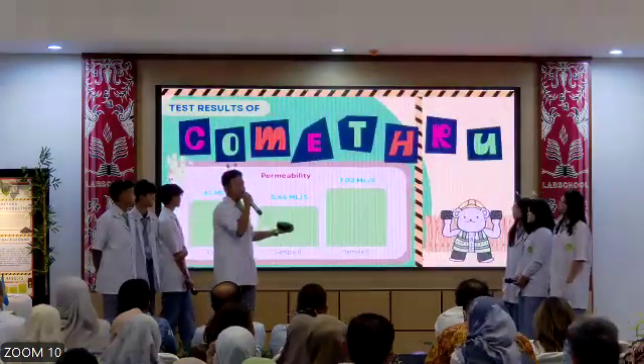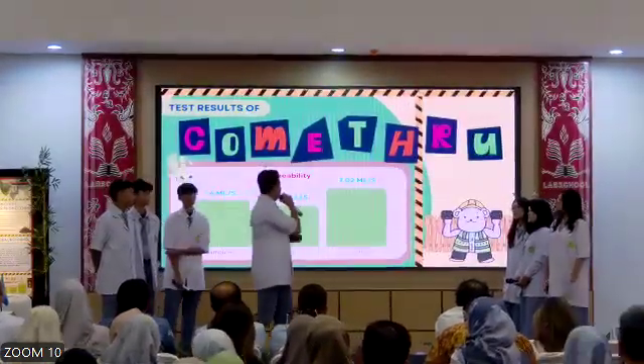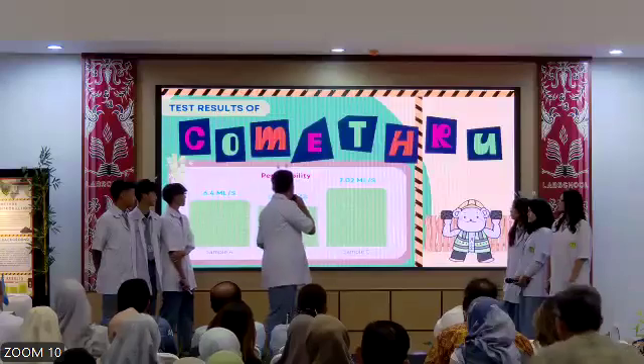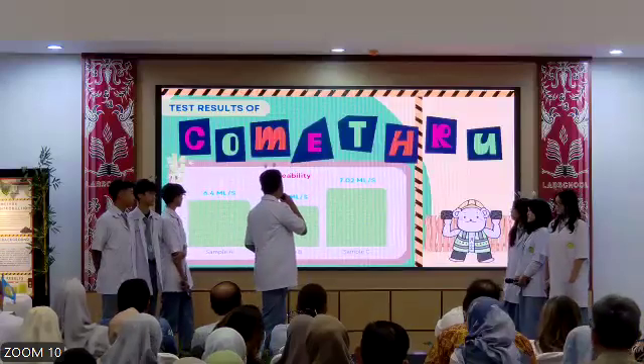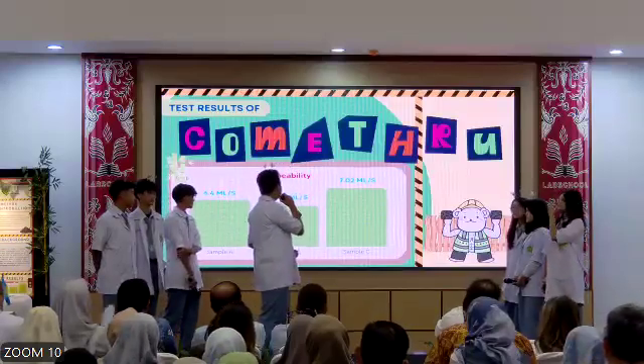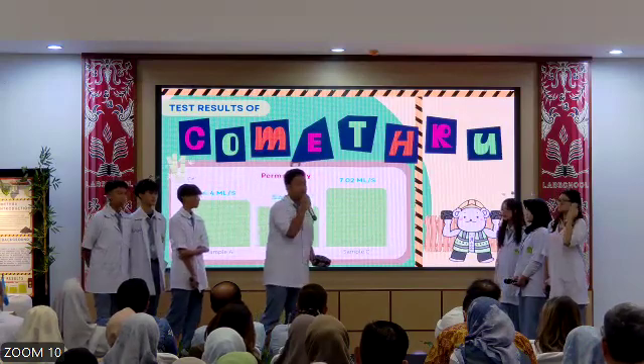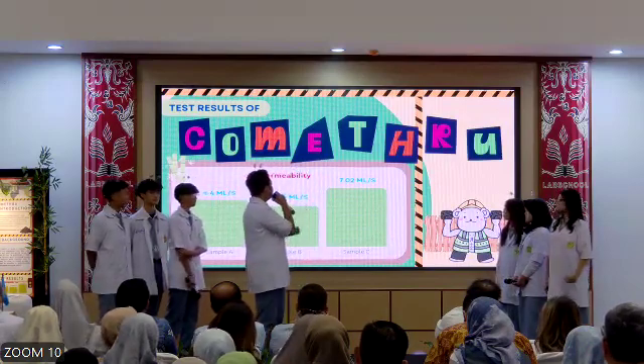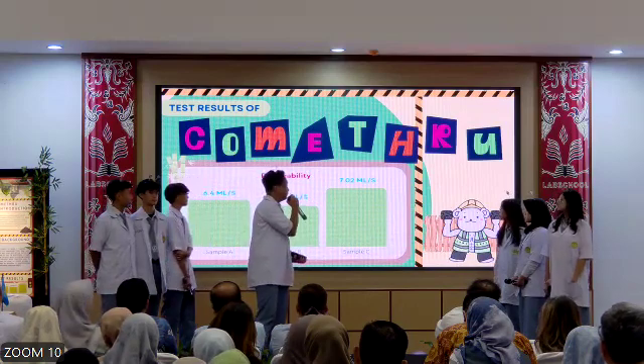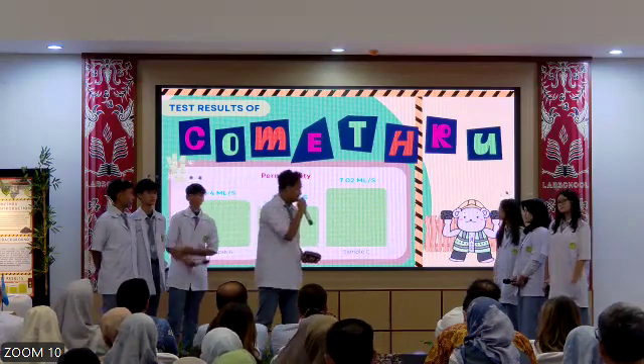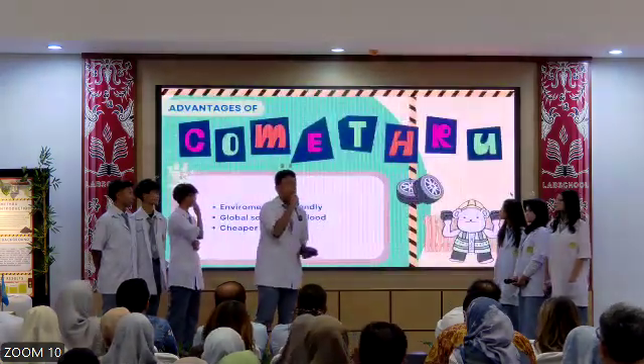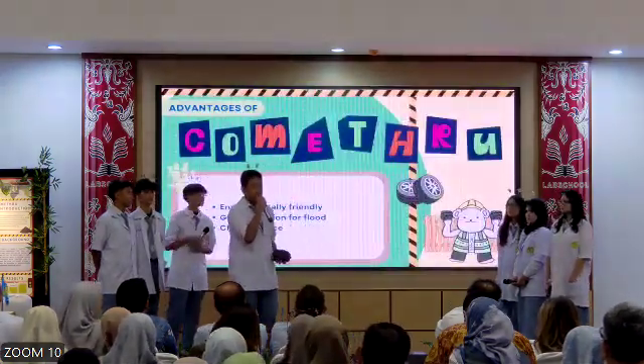This is our result of the permeability test. Sample A is 6.4 milliliters per second, and sample B is 5.64 milliliters per second. The last one is sample C, 7.02 milliliters per second. Permeability is how long the water takes to go through the pores of the asphalt.